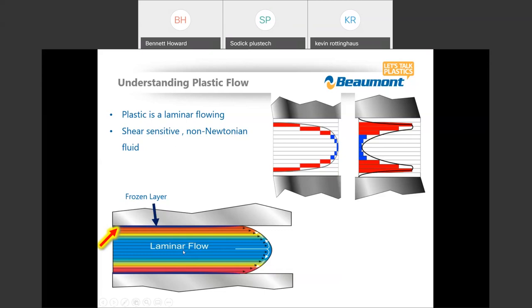Again, plastic is laminar flow. We end up forming different laminates in the runner system. The first laminate that develops is going to be our frozen layer or frozen skin. It's a very thin layer of plastic against the steel wall here. Once this laminate lays up against this steel, it never moves again.